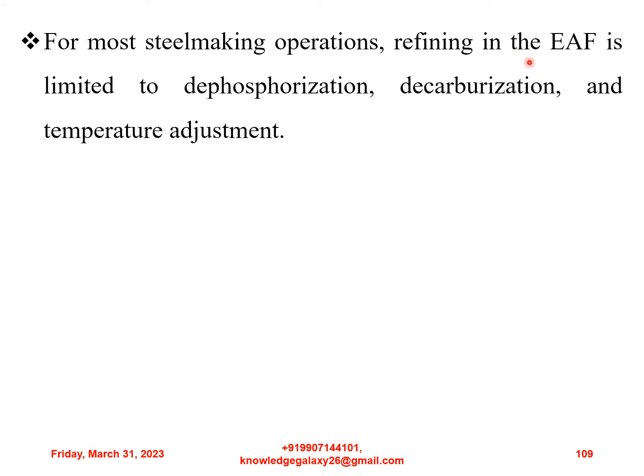At the end of refining, a bath temperature measurement and a bath sample are taken. If the temperature is too low, power can be applied to the bath. This is not a big concern in the present day steel melting shops where temperature adjustment is carried out in the ladle furnace. For most steelmaking operations, refining in the electric arc furnace is limited to dephosphorization, decarburization and temperature adjustment.